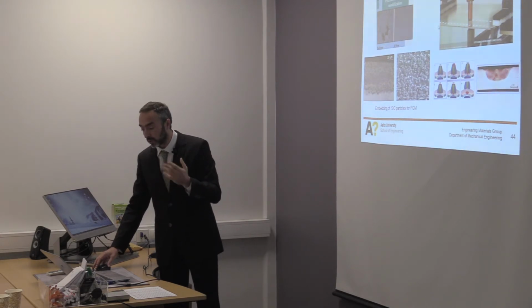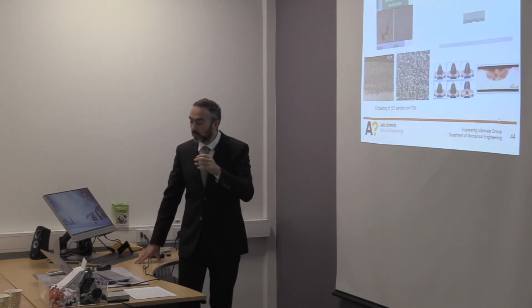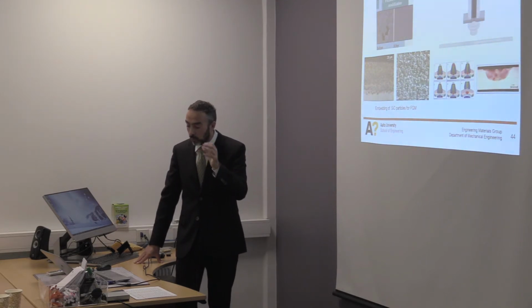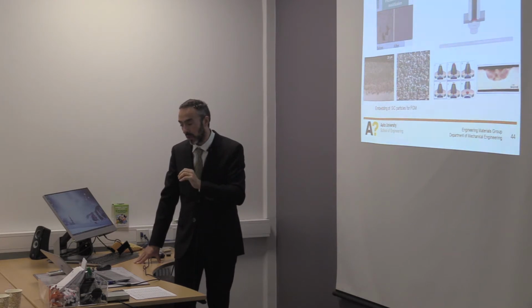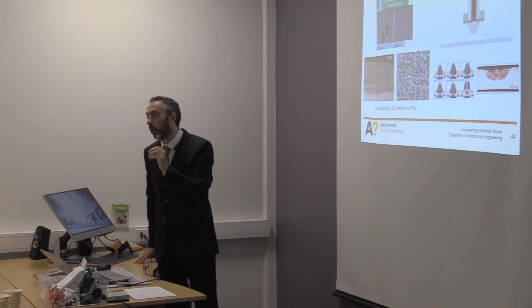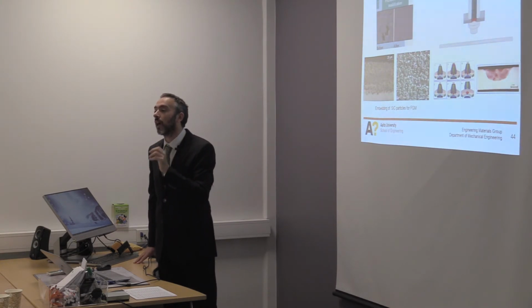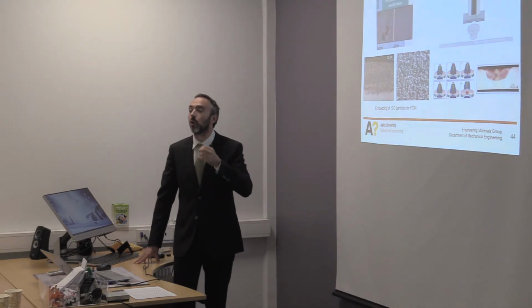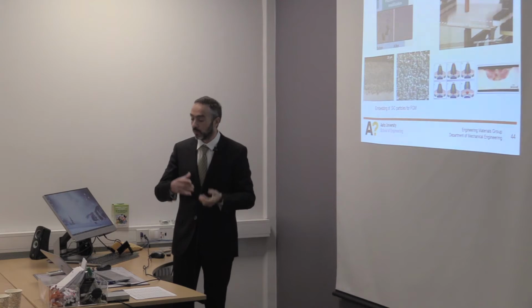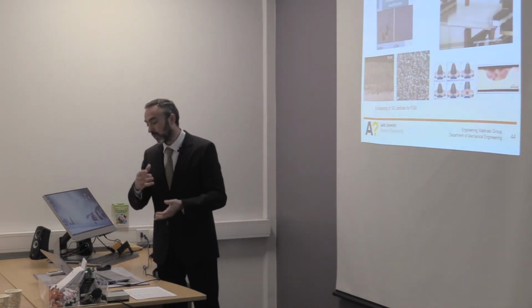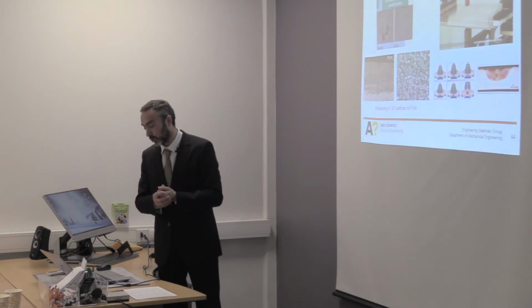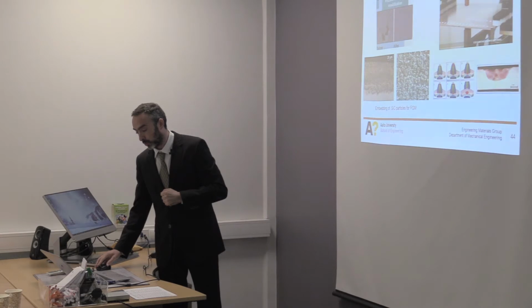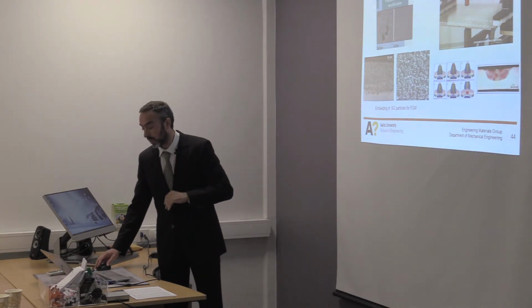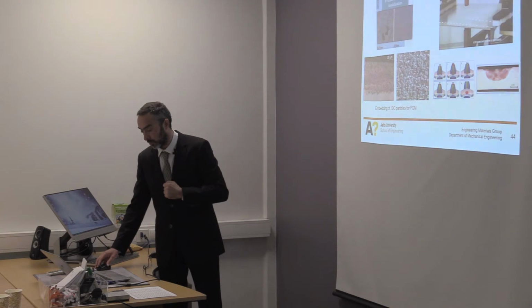One field of important development nowadays is this friction stir spot welding, where there is no melting of the components, and the spot exists, as we know, in resistance spot welding. This is achieved with 2 rings and 1 probe, 1 body. The middle ring and the internal body goes in rotation, opposite rotation, and vertical movement, and compensate the flow of material. This viscoplastic flow of material will have a penetration that overcomes the top thickness and enables the full spot joint. We have new standards that are almost ready to be applied in the multiple variants for this friction spot welding and friction stir and so on.